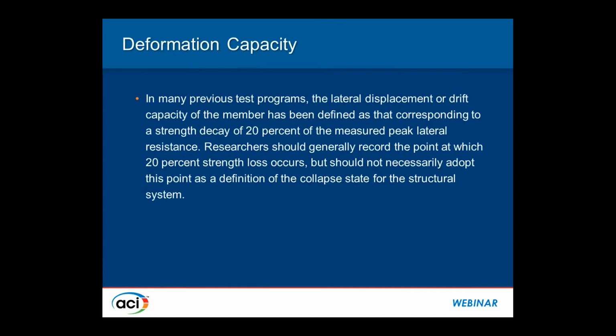And then this is the onset of inelasticity. The capacity is dictated by the end of the inelastic range, which is when the specimen is beginning to fail. And typically, researchers have used in the past 20% strength decay as an indication of member failure. That by no means indicates structural failure or building failure. In a multi-story, multi-bay structure, individual elements may undergo excessive strength decay, but the structure itself may not experience that.